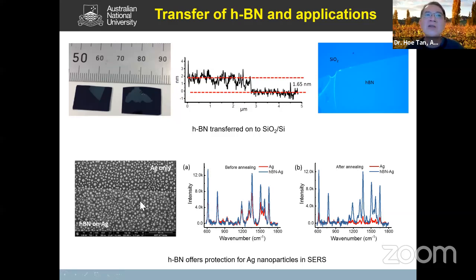And what we did is we use this to demonstrate the passivation property in SERS application. For example, here you have silver nanoparticles for SERS application. So as you know, silver is a good plasmonic material. It can enhance the sensitivity of Raman signal. Okay. But the problem with silver is it oxidizes very easily. So by putting a layer of HBN on top of this silver particle, and even after annealing here, at 400 degrees Celsius, and this is the Raman signal from a rhodamine solution. Okay, as you can see here, if you don't protect the silver particles after annealing, the SERS signal is gone. Okay, but if you protect this with hexagonal boron nitride, you can see the signal still remains even after 400 degrees annealing. So it's a very good passivation layer.